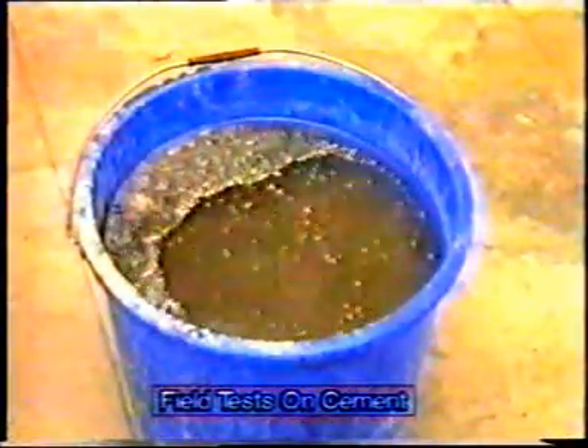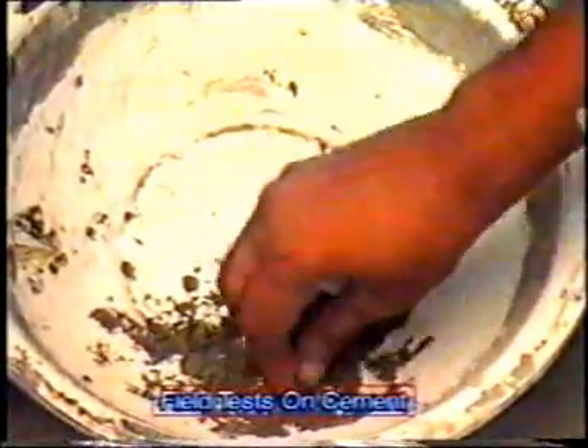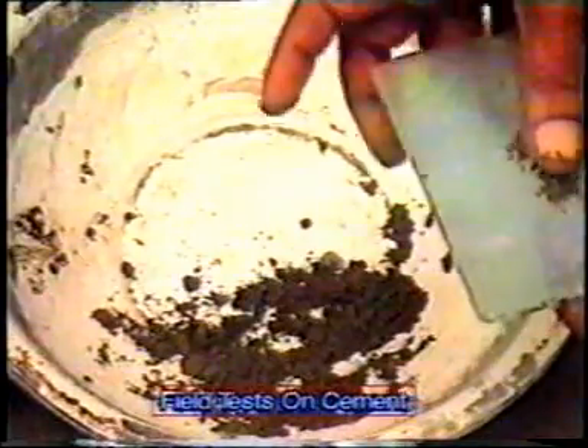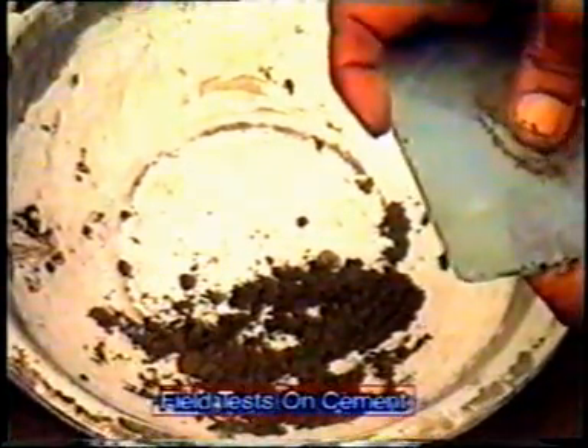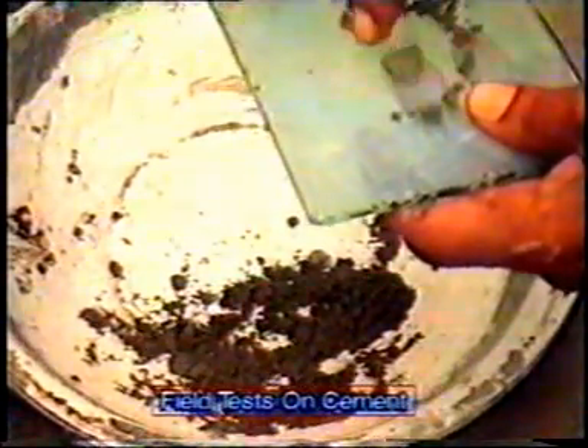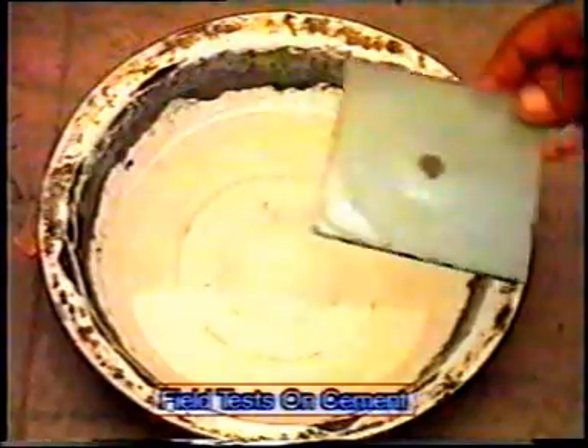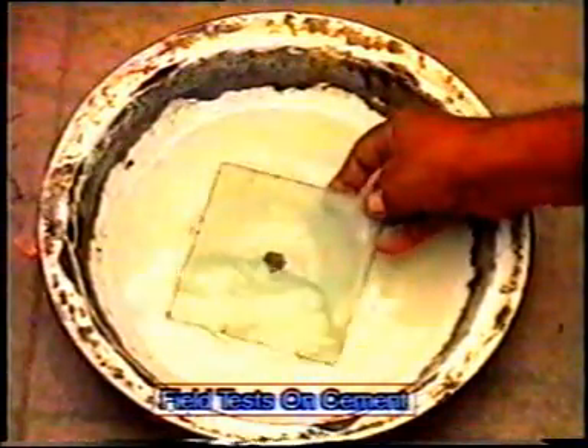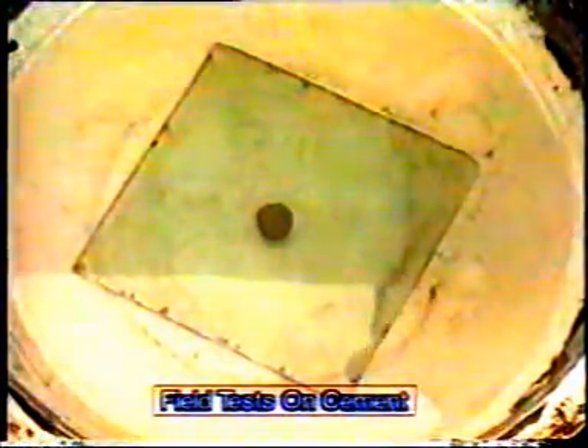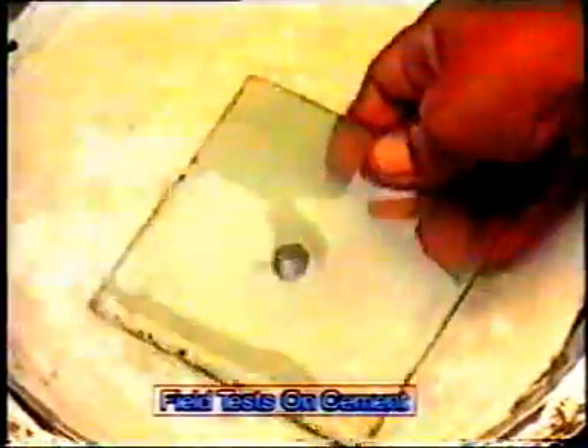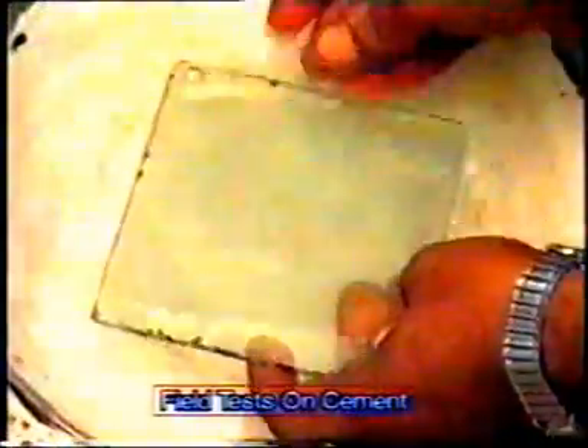Take a handful of cement and throw it on a bucket full of water. The particles should float for some time before they sink. Make a stiff paste of cement and make a cake with sharp edges. Put it on a glass plate and slowly take it under water. See that the shape of the cake is not disturbed while taking it down. After 24 hours, the cake should attain some strength without change in its shape.